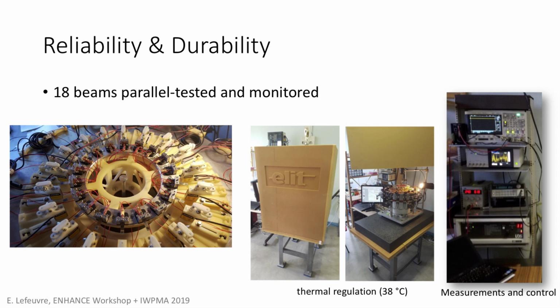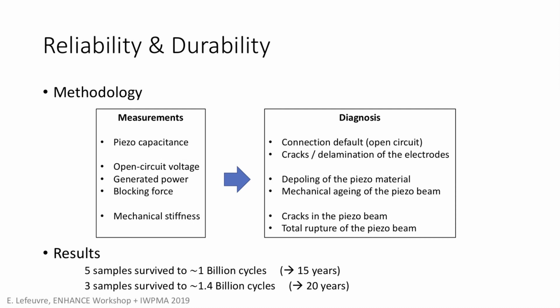So what we measured actually: the piezo capacitance, the open circuit voltage, the power generated on a resistive load, and the blocking force of the piezo. So you stop the system, you apply a voltage, and you monitor the force at the extremity. And we measured also the mechanical stiffness in open circuit, doing just a displacement and measuring the reaction force. All these measurements are needed to understand what happened to a sample that stopped working. Because that was the idea, to understand well the weakness of the samples. And that's very important to understand where the problem comes from to solve it in an efficient manner.